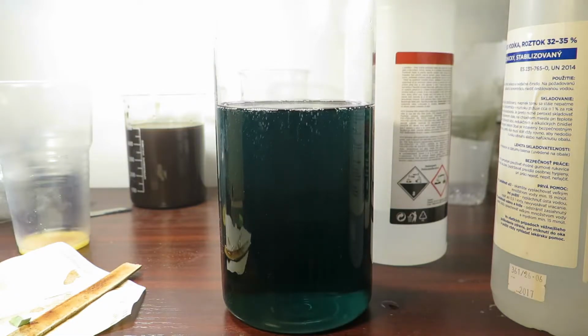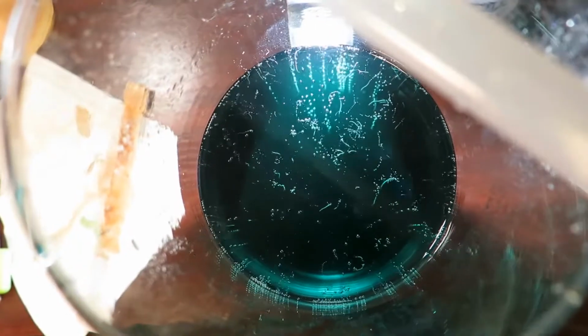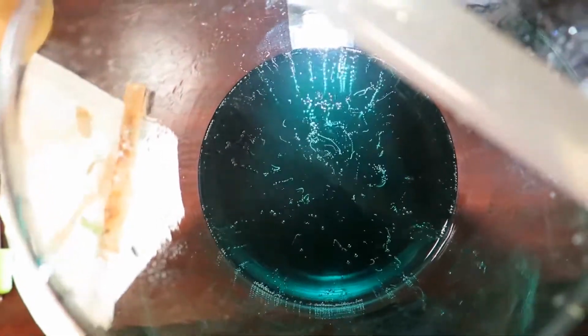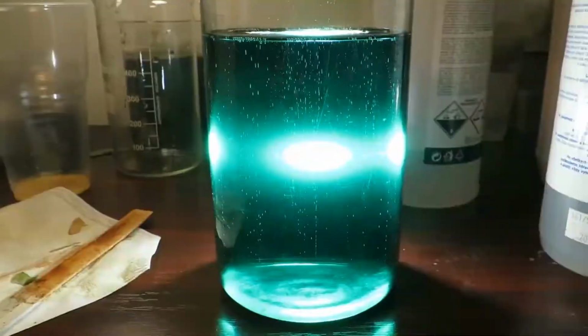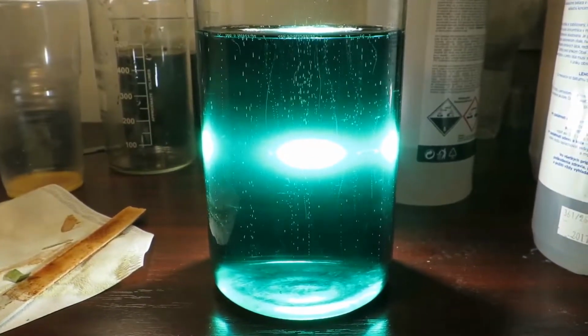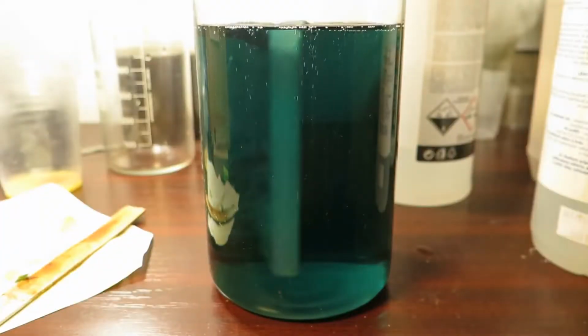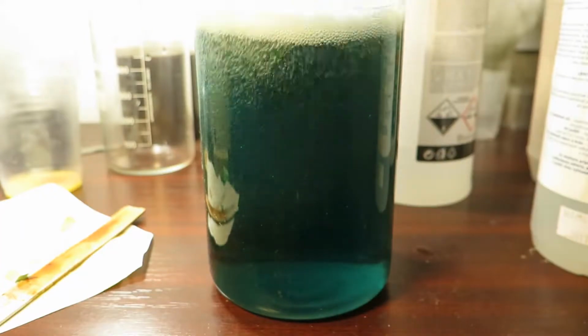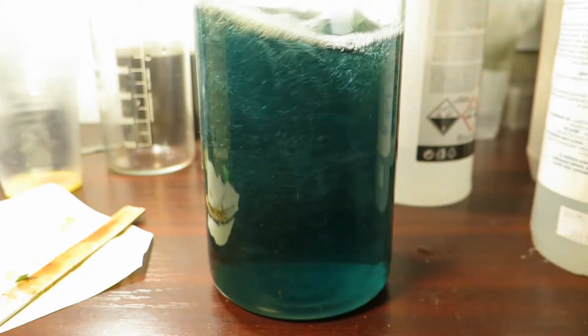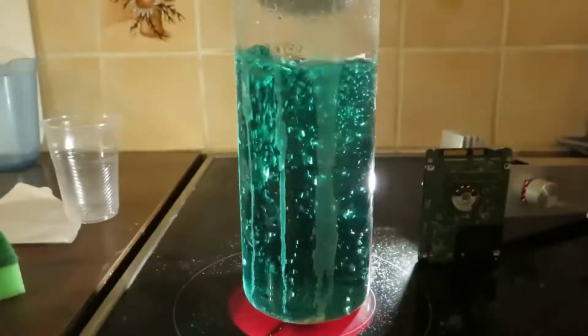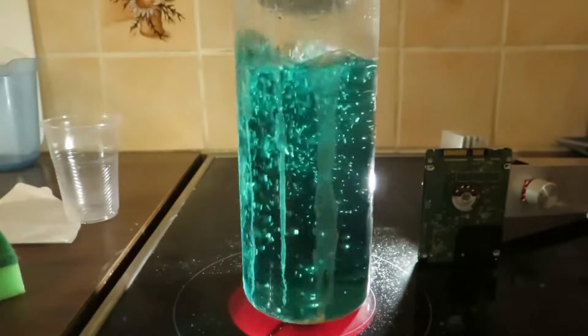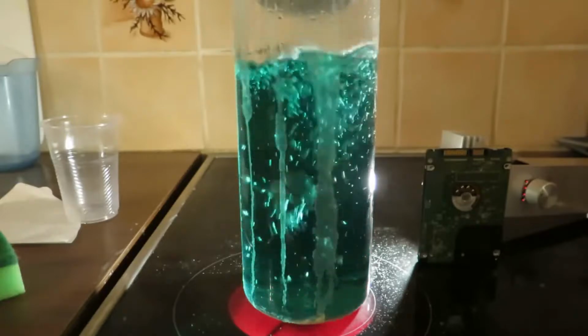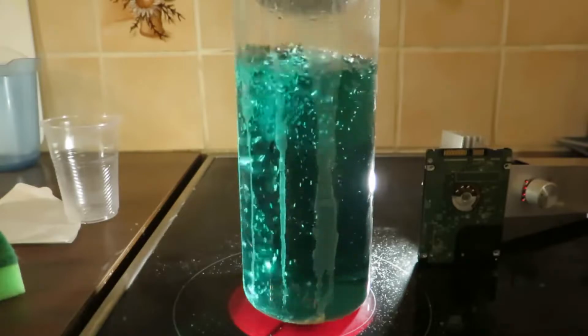This camera is not 100% correct in the color representation, but it's fairly close. Now on a smaller scale this reaction is quite fast. I was a little bit afraid, to be fair. Okay, so what we are left with is chromium(III) sulfate, chloride, or whatever acid you added in. And now that the solution is a little bit safer to handle, we can remove the hydrogen peroxide. This is usually done by boiling the solution, so off to the hot plate. After about half an hour of boiling, we can let this cool and proceed to the next step.